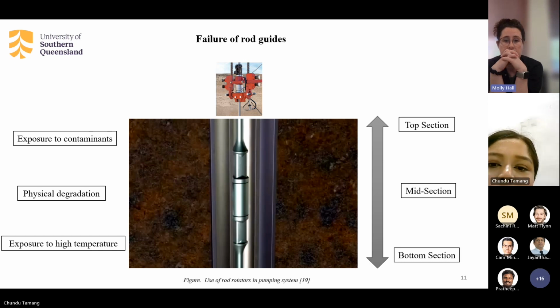So what the operators do, in order to make sure that the wear of the rod guide is not just one-sided but is evenly distributed, is often use rod rotators. But the effect of using rod rotators is usually the best at the top section. However, in the midsection, the wear starts becoming uneven, and it is at the bottommost section that the rods are severely worn, broken, missing parts and mechanically damaged.